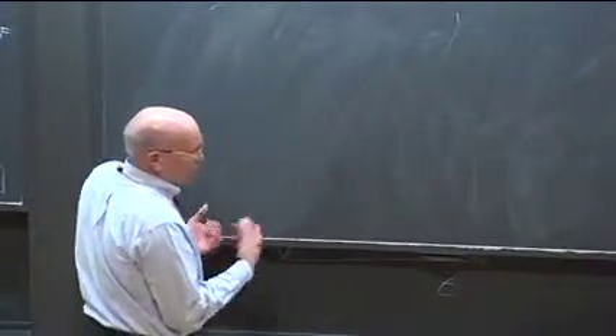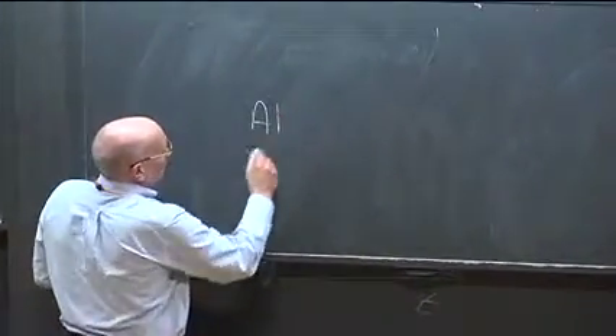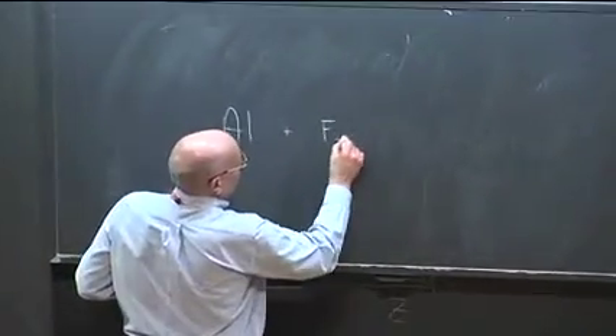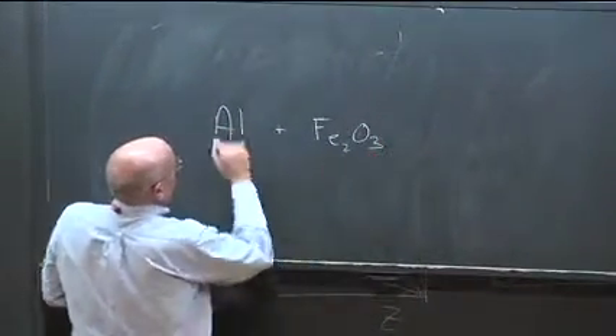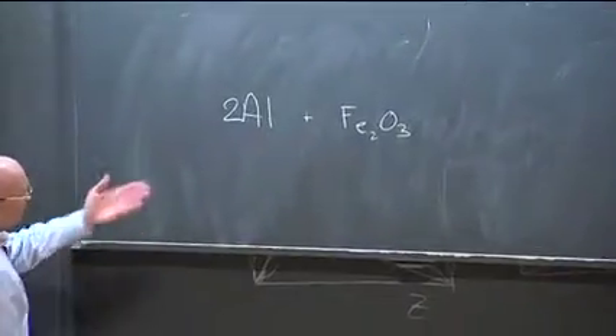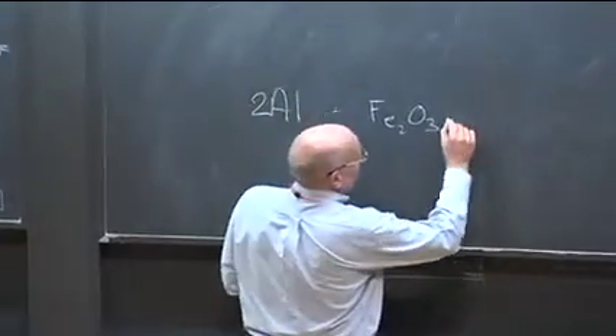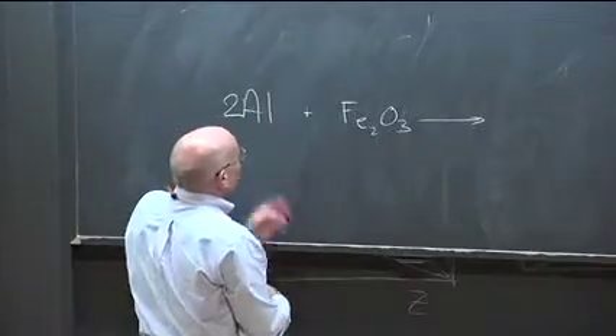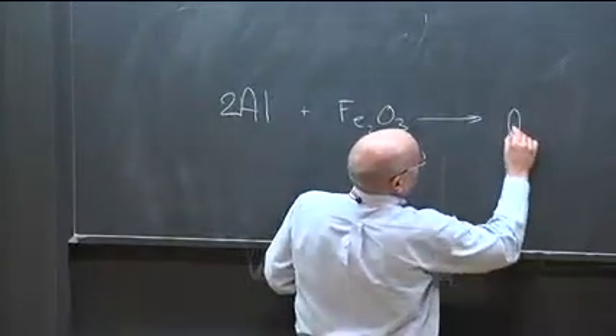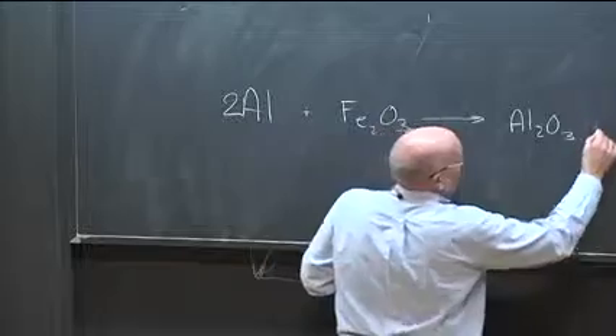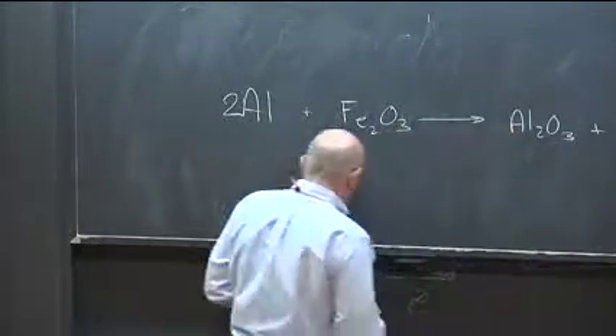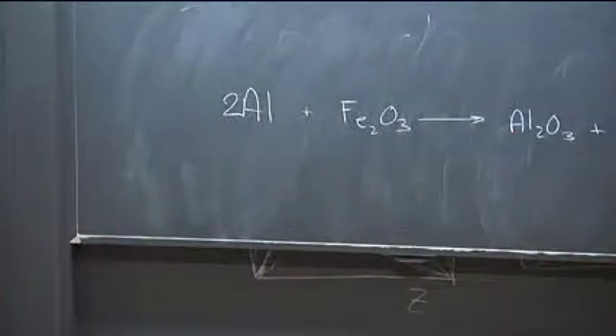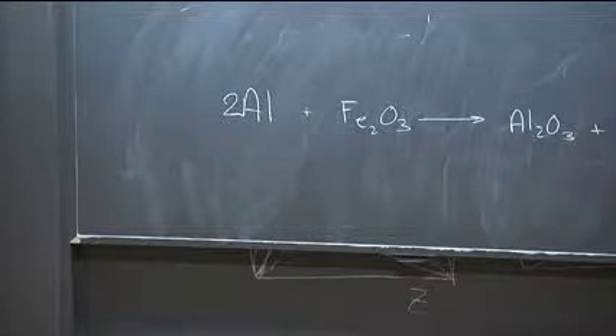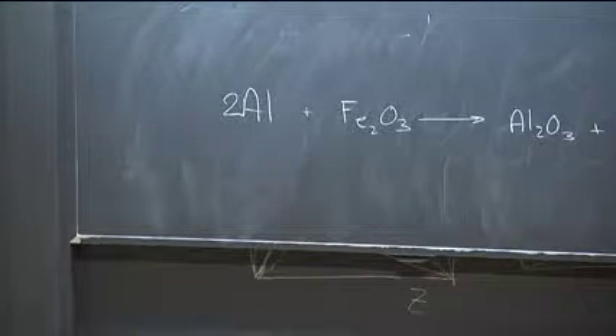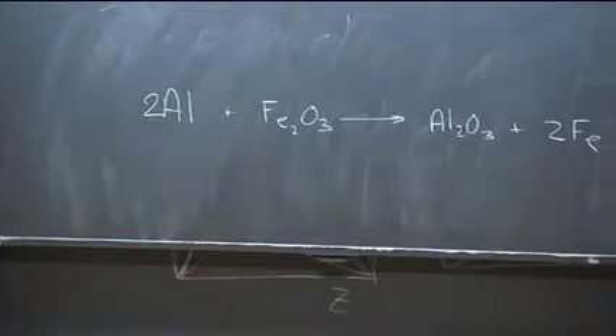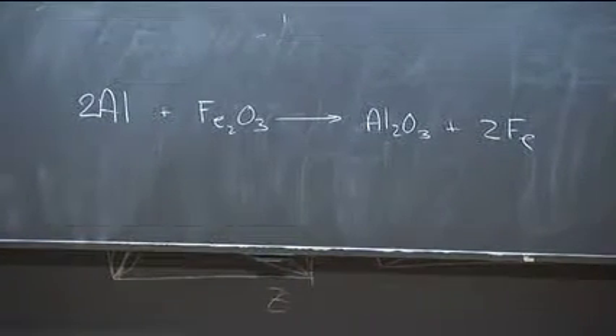So say, for example, I wanted to react something like aluminum with iron oxide. And in this case, suppose I react 2 moles of aluminum with iron oxide. I could actually, if this is an exothermic process, I could actually drive the reaction to make aluminum oxide plus iron. So the reason I bring this up is because this sort of field has been very important in terms of material synthesis, using thermite-type reactions, intermetallic reactions to make certain types of materials.